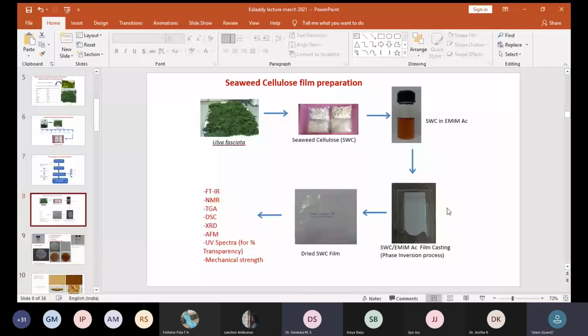You can continue. Okay, so what we did, instead of making only the pure cellulose film, we tried to make an in situ silver nanoparticle loaded film. And sometimes we also did the neem leaf. We took the extract and we made the film. In most of the cases, these films are very rigid and transparent. So what I am trying to say is, from the green seaweed, we are able to extract the cellulose, dissolve it in the ionic liquid, and make a film of very suitable quality as a food package or some wraps.